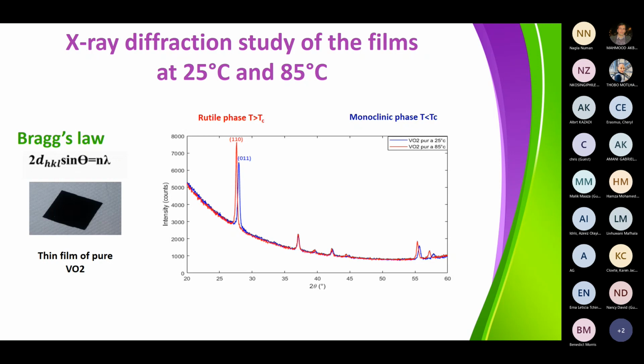And if you do the theta to theta scan in the insulating phase and in the metallic phase, you will see that there will be a little bit of a difference. So typically, you can see that the major difference that you can observe when you go from low temperature to high temperature is that this peak is shifting. And actually, if you try to calculate it, you will find out that you go from the monoclinic phase at room temperature into the rutile phase at high temperature at, in this case, 85 degrees Celsius.